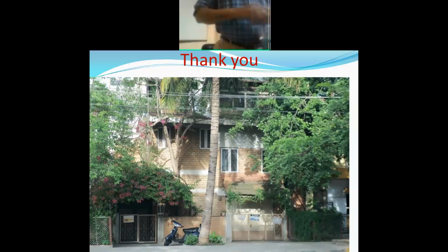Thank you. Actually, I have two questions. For the first part, when you produced lime pozzolana, which you said is probably equivalent to GGBS, what we are getting now, were any tests done to ascertain the percentage reactivity of calcium oxide and reactive silica? Some tests, whatever was available at that point. Yogananda's MSc thesis has a lot of information, and we also have a paper on use of rice husk ash and burnt clay as pozzolana. So we have found that 70 to 80% of that material will be reactive in nature, like GGBS.